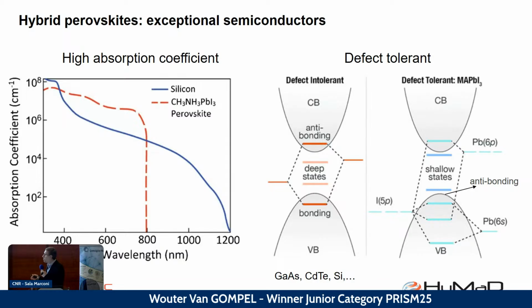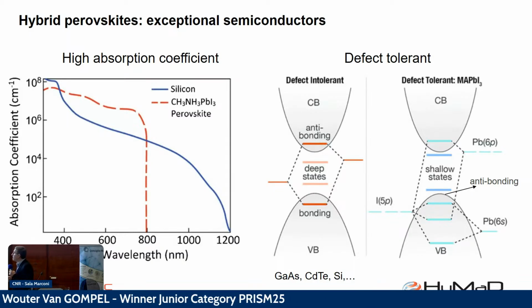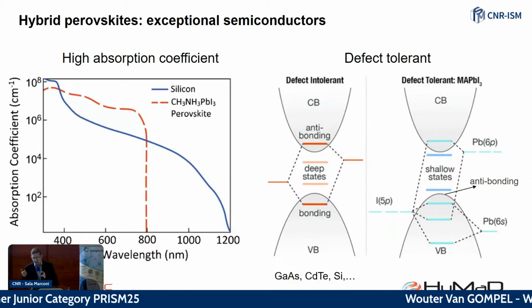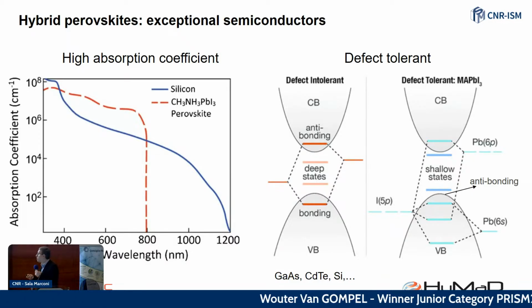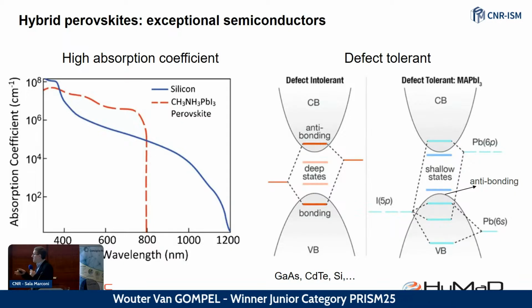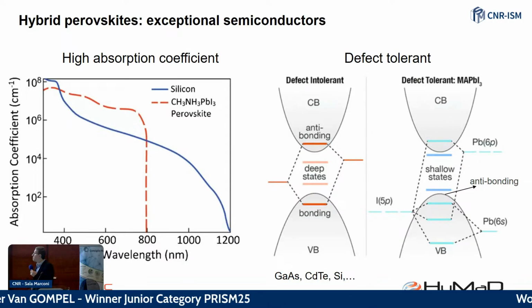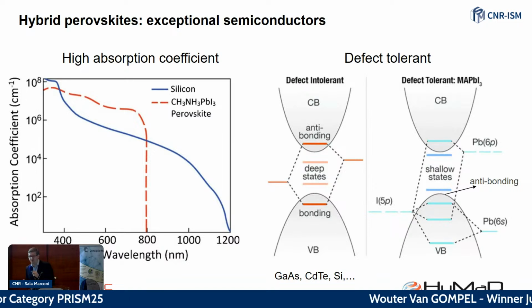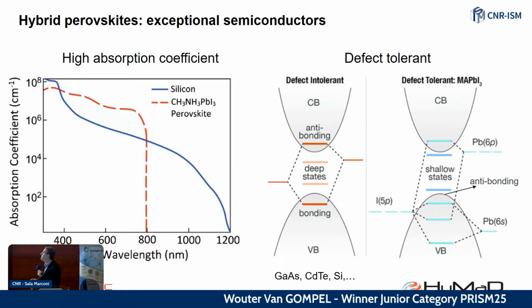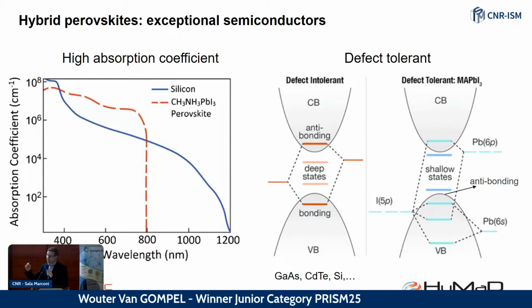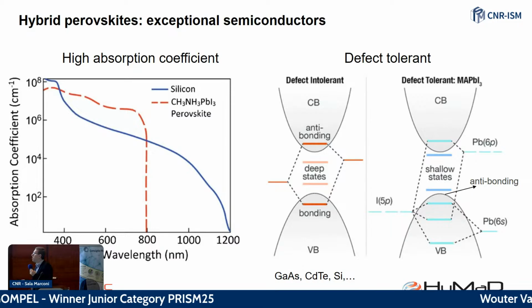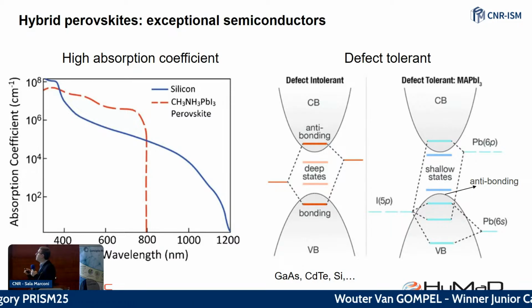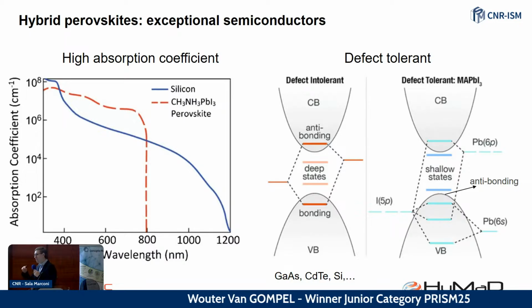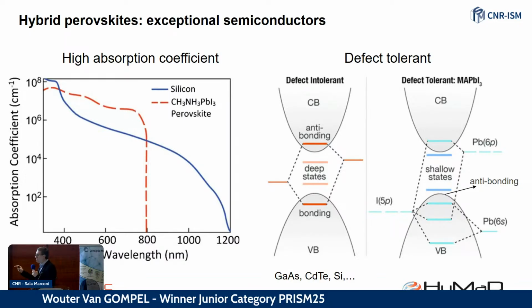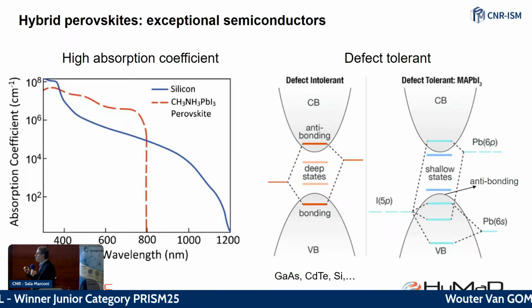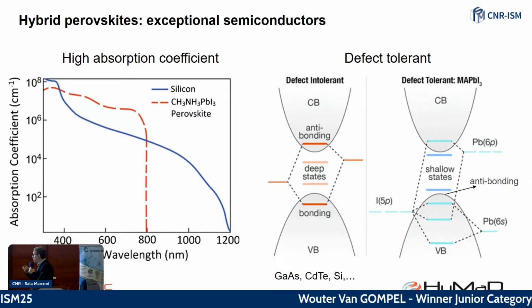So you could say that they are quite exceptional semiconductors, especially for optoelectronics. So why is that the case? Well, firstly, they have a very high absorption coefficient. If you compare it to silicon, which is of course still the reference in the relevant wavelength range, it has a much higher absorption coefficient, which is linked to the fact that this is a direct gap semiconductor. And it, of course, has the advantage that you can go to much thinner absorbing layers and still absorb the same amount of light. So you can start thinking about applications like flexible solar cells, for example, because you can really go to 300, 400, 500 nanometer thick absorbing layers, which is, of course, very interesting towards applications.